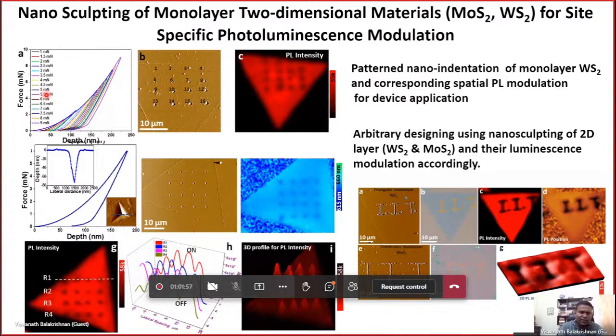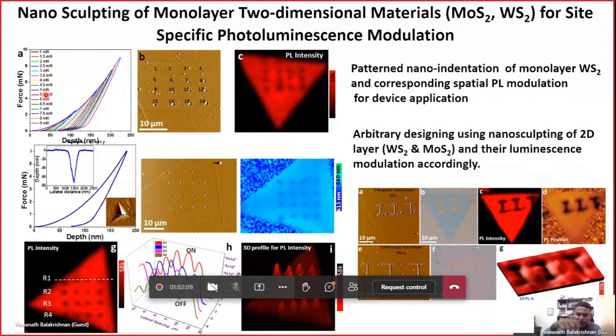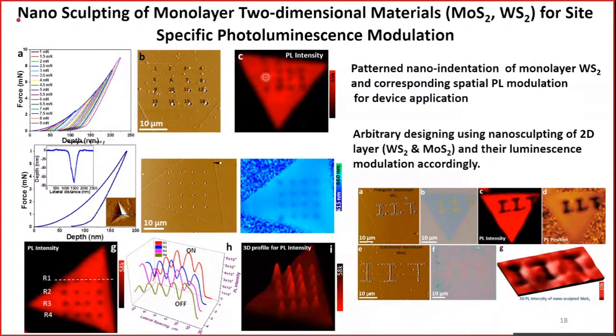So nano indentation is a very simple technique to measure the mechanical behavior. It is a very sharp diamond tip with the application of force. We can essentially touch your 2D material, and with the increase in further load, we can selectively make a sculpting. And since it is a nice 2D transducer, we can make any pattern that we want. We can select the position. We can also select or change the actual load or the stress involved. So we are able to do this kind of selective sculpting by the arrays of nano indentation.